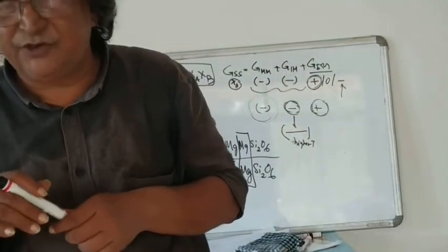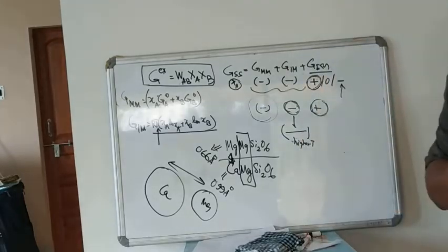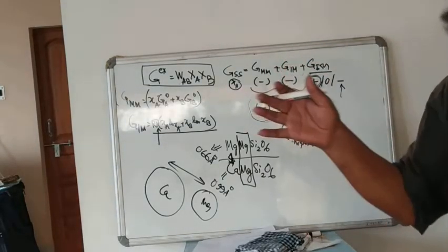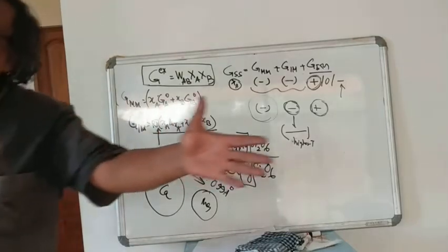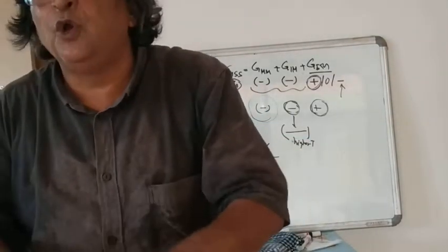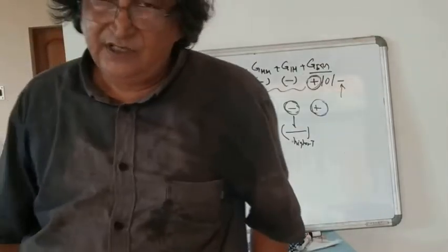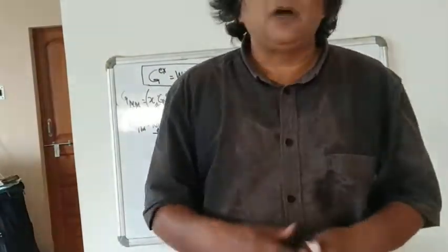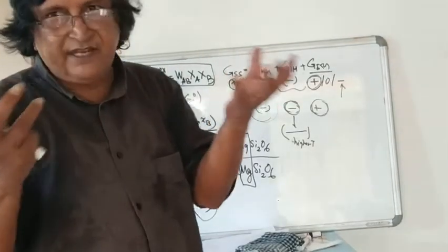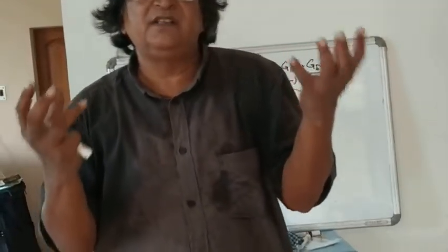So what happens? Plagioclase commonly shows exsolution. You may think that plagioclase does not have exsolution, but plagioclase has lots of exsolutions. You are only shown the high temperature plagioclases, that is why you don't see it, but at lower temperature, plagioclases show tremendous amounts of exsolution. There are about three exsolutions, Bøggild, Huttenlocher, and there are three more solid solutions at different lower temperatures. Of course, at higher temperatures, they are great friends. But as the temperature lowers, they separate out because this sodium and calcium cannot be accommodated in the same crystal structure.